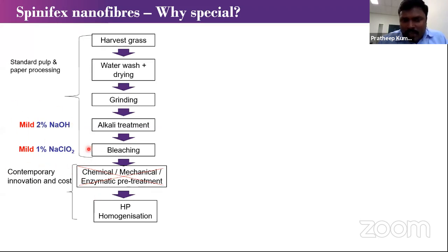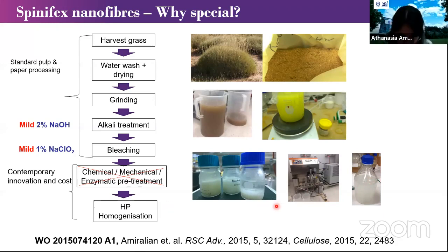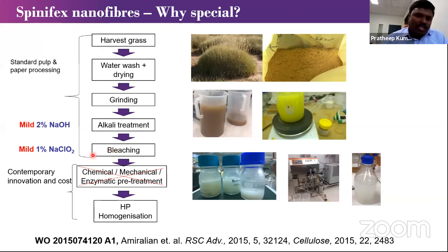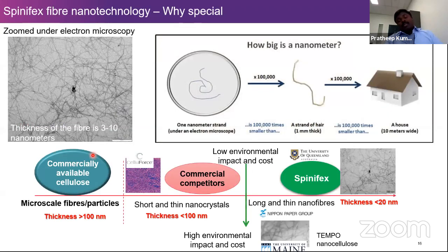You can see that this requires really mild chemicals, and you can make nanocellulose out of this. In some cases, you don't need to even bleach it. You can leave the lignin or hemicellulose within the nanofibers. And when you compare with other developments in nanocellulose, this compares the length and thickness ratio. In this ratio, you can see the spinifex stays on the top, where we can make really long and thin fiber with really reduced environmental impact and cost. We don't use much oxidizing chemical to get this kind of thinner nanofibers, like others do, okay.